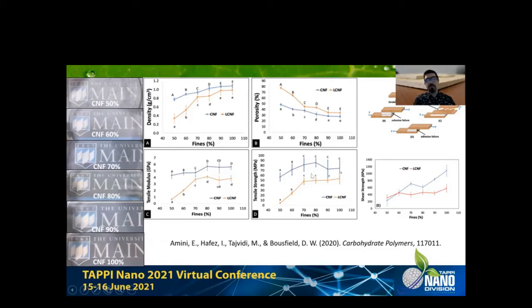So basically for our properties, and in addition, if you do these shear strength tests or lab shear tests, you can also get an idea of the bonding properties, and they also kind of level up at about 70% fines. So the conclusion is that for these applications that we are concerned about, we really do not need to go that high in fines content.